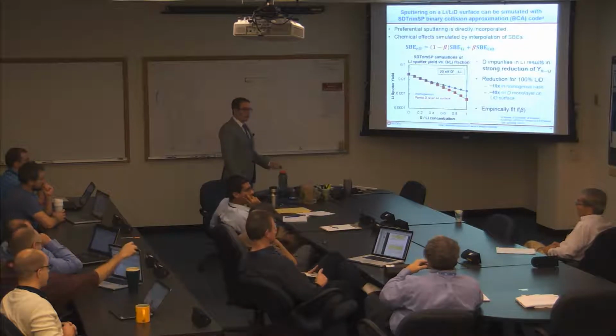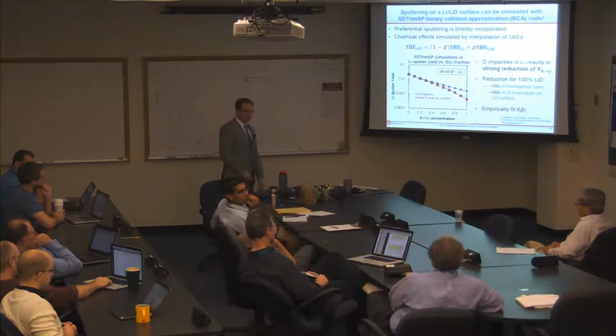So every monolayer has the same beta, is how you're doing this? Every monolayer, other than in the red case, where the top monolayer is enhanced. And in the blue case, every monolayer has the same concentration. But you have to remember, you only have to simulate the first 50 or 100 nanometers. You don't need to simulate 50 microns of material or something like that.